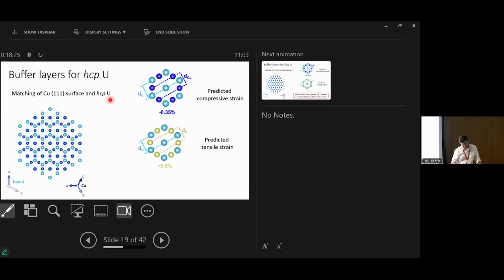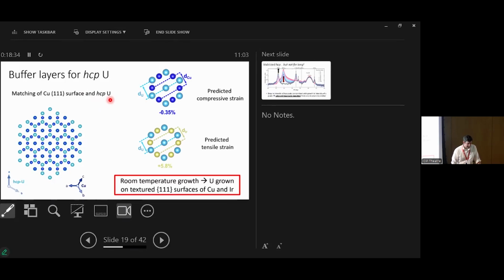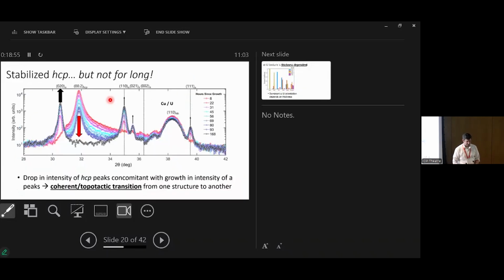She also found a slightly related one with iridium. So iridium was also a templating material with a slightly tensile strain. Okay, so what we did was a very simple thing. Forget single crystals and high temperature growth and all fancy things like that. Actually, room temperature growth, the copper and iridium like to form in this 111 close packed surface. So we just did samples of copper and iridium, and then we grew uranium on top. And we could do that. So we stabilized this hexagonal close packed phase.